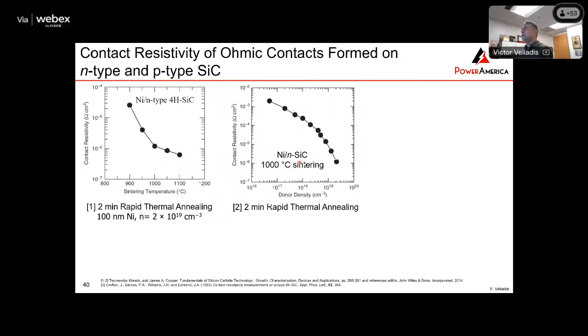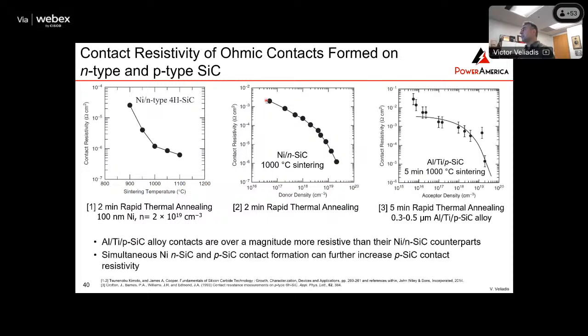If you look at this one here, this is annealing at 1,000 degrees, and you can see that the higher the density, the doping of the area where you're forming the contact, the lower the resistance. So to form ohmic contacts, you need to dope at 10 to the 19th and anneal at 1,000 degrees to be at this point. If your doping is at a lower level, then your ohmic contact is very resistive, which is undesirable. And this one here shows the case for the P-type. This was the N-type, this is the P-type.